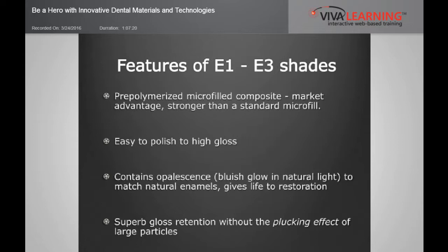And I told you that the microfill composite is made of super small particles. So over time, when we lose some particles on the composite, we won't get that plucking effect of larger particles. This is a problem with the older version of hybrid composite. I mean, you lose large particles on the surface of your composite, and what you get is a very dull surface and a rough finish over time. And of course, this is not what we want to have.